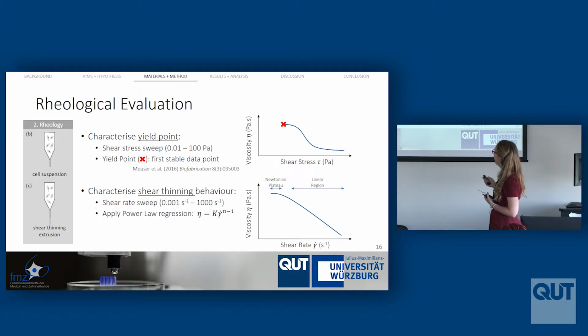So we wanted to look at the yield point. This is when you start to apply increasing forces to the material, and it then starts to flow as a liquid. This is really key for us: we want the yield point as the first stable data point in this particular flow diagram, and this tells us if the material will be able to suspend those cells or not. And then the other one was looking at the shear thinning. So as we ramp up the force that we apply, we look at how the viscosity decreases, so it turns more and more like water as we apply more and more force.